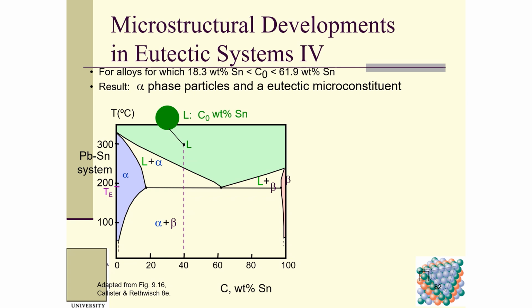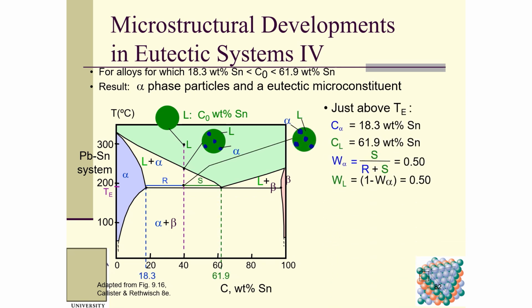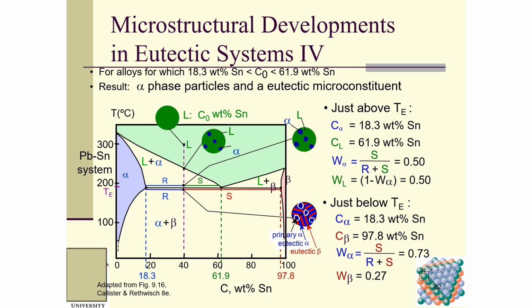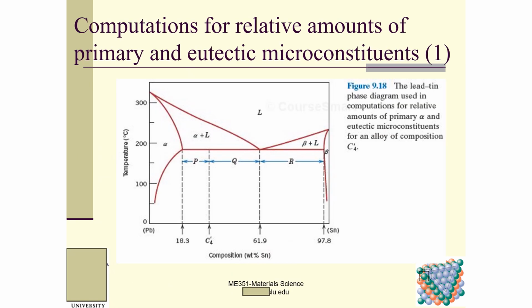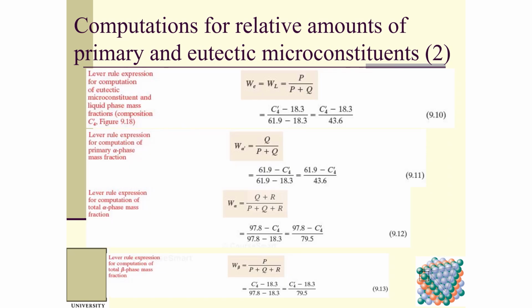This eutectic, for another range. So this is the L plus alpha. So it is still alpha plus L. Can still use the lever rule. And so here is a primary alpha, eutectic alpha, and this is eutectic beta. Okay, eutectic alpha and eutectic beta, and they form the lamella. And the primary alpha is the alpha we got here, and it is just like balls here. It's very, very beautiful. Then computation for relative amounts of primary and eutectic microstructure, and we draw a line here. Okay, P, Q, and R. So these equations, I want you guys to take a close look at these equations.